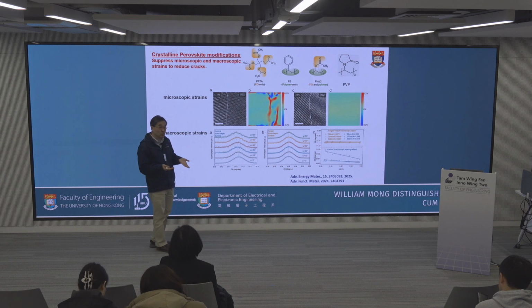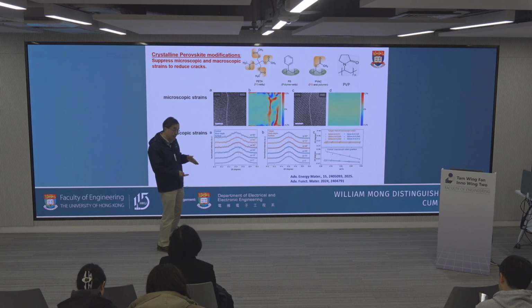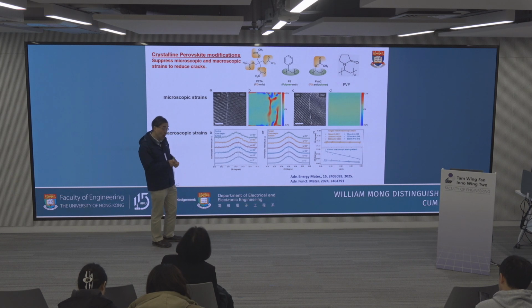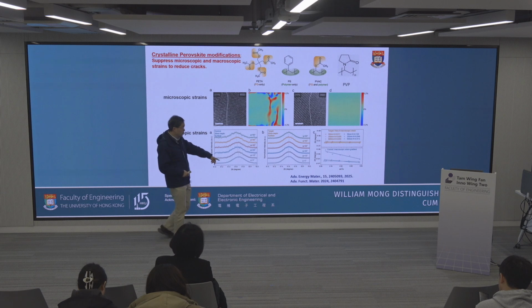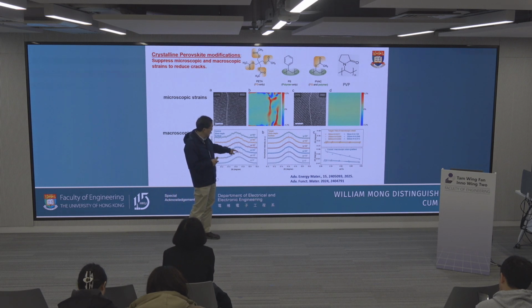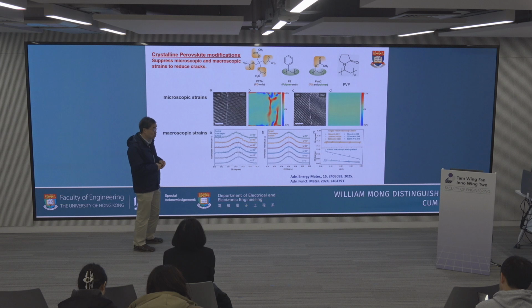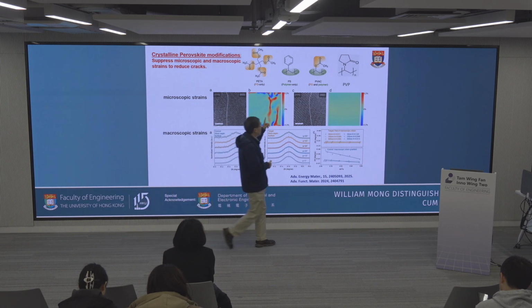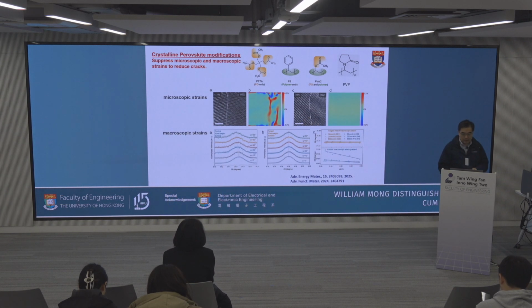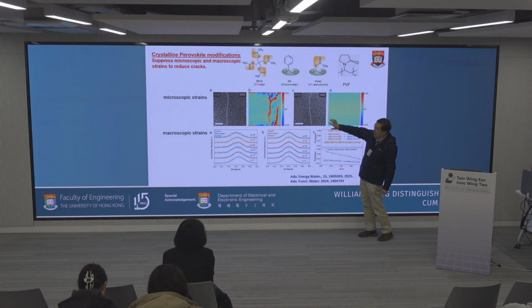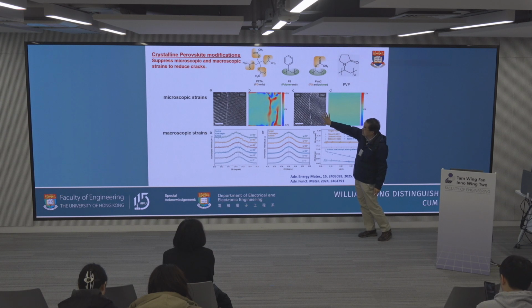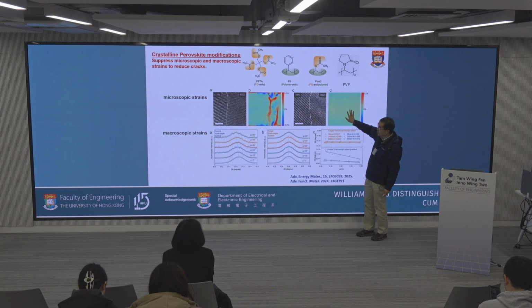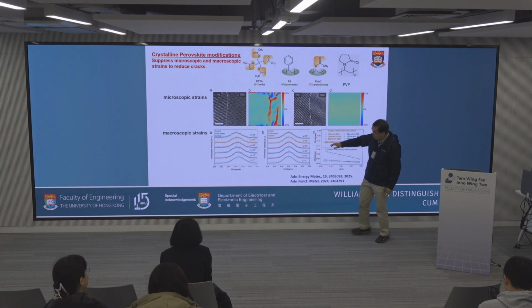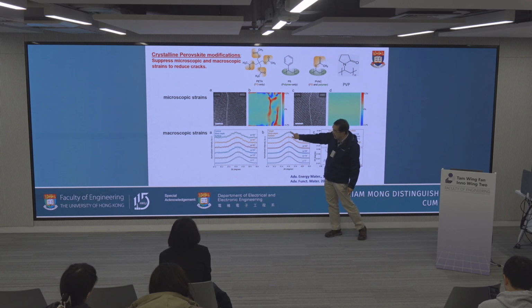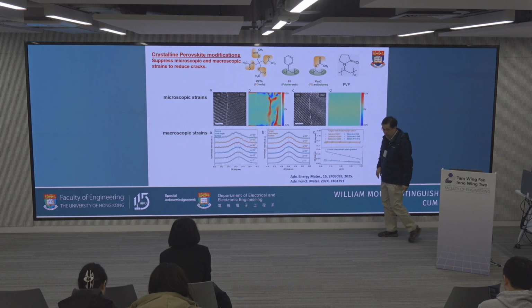On the other hand, because we use solution processing, the composition cannot be exactly uniform from the bottom to the top in terms of the perovskite composition. So the change of the composition eventually creates another stress. This is a macroscopic stress. So what we do is introduce some different small molecule in synthesizing the perovskite. It can help us to release the stress that we originally have in the control device. So in this device, we still have the grains, but we don't have a strong stress anymore. And also in the vertical direction, we find from the XRD that we don't have any obvious peak shift.